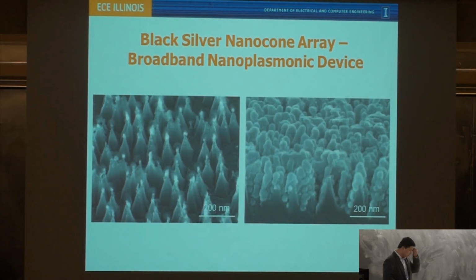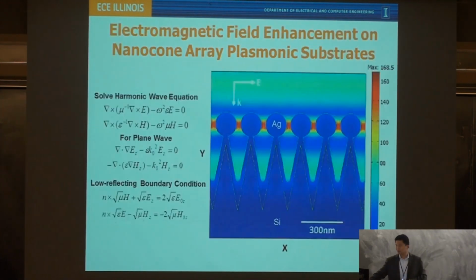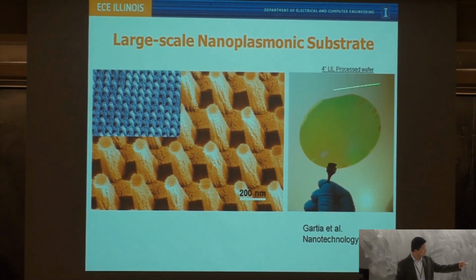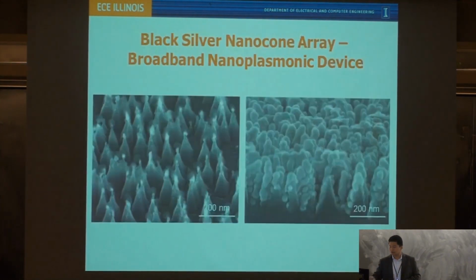Now comes the question, how do we make them more efficiently and at lower cost? So besides of those very fancy fabrication technique like this method, we also discover a very low cost but a very high efficient way to make silicon nanocone arrays with very high density, very small features. And then we can deposit metal like silver or gold on the surface to create a pseudo-uniform or ununiform, you can say ununiform nanoplasmonic substrate. But in some applications, this is even better than ordered plasmonic array because the following reasons.